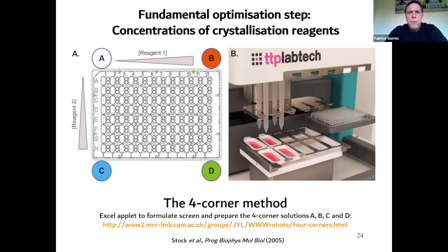But for the first step, to investigate the concentration of the main component, we're using the four corner method, which is ideal for this. And there's some preparation to do. We have an Excel applet available on the link there at the bottom of the page. You can go and see that. That will help you to formulate the four corner solutions that you require to do this screen. You will bring those four conditions that you prepare manually in tubes to the liquid handler. We have the Dragonfly to do that. Very straightforward protocol again. The robot is going to mix the four solutions that you prepared at different ratios across the plates, and you will end up with a nice two-dimensional gradient of concentration screen.